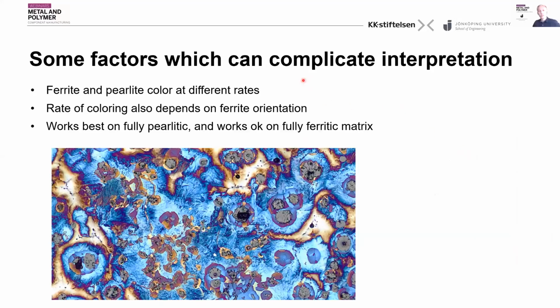Another factor that can make it a bit more difficult to interpret the structure, at least in terms of solidification sequence, is that ferrite tends to etch at a slower rate than the pearlite, which means that the pearlite becomes blue earlier than the ferrite does. This is of course good if you want to see the ferrite, but it can mean that the correlation between the silicon concentration and the color is not as simple in this case. The rate of coloring also depends on the ferrite orientation. So you can see that some of these ferrite grains are a bit more blue and some are a bit more yellow. So if you want to see the solidification structure, the color etching method works best on fully pearlitic or fully ferritic materials.